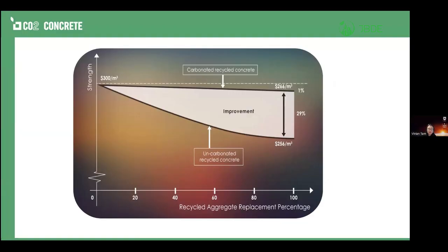That is how this carbonation process works. You can also see on this slide what virgin concrete looks like. If we purely replace virgin aggregate with recycled aggregate, at 100% replacement, the strength goes down about 30%. But by injecting carbon dioxide in, the strength goes back up, matching the performance of virgin concrete. Not only does the performance increase, the cost is also efficient. In rough data, it is about $300 per cubic meter for virgin concrete. Because recycled aggregate in general is about half the price of virgin aggregate, the cost goes down, but the strength also goes down. By injecting carbon dioxide into the recycled aggregate, the strength goes up, and although the cost goes up, overall we still have about a 10% cost reduction in the 100% CO₂ concrete compared to virgin concrete.